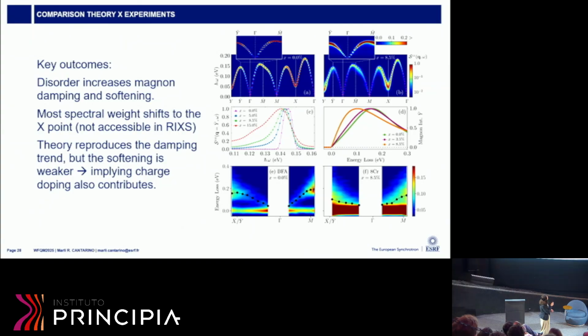Then I can have the cuts at the Y-bar point, which is the maximum momentum I can reach in my experiment, going to the pi-0 direction here. As a function of doping, we see this bigger width of the excitation, and also the transfer of spectral weight towards smaller energies.